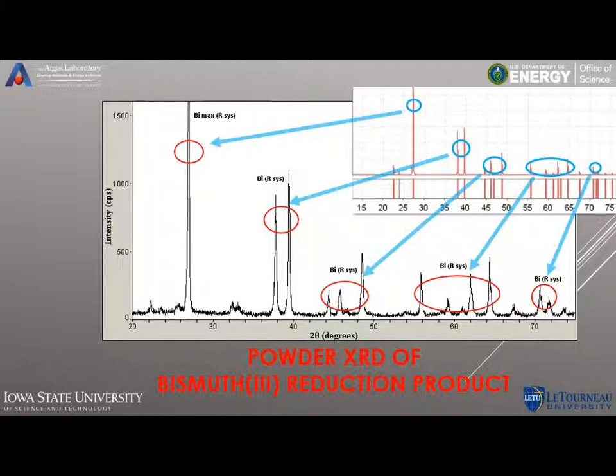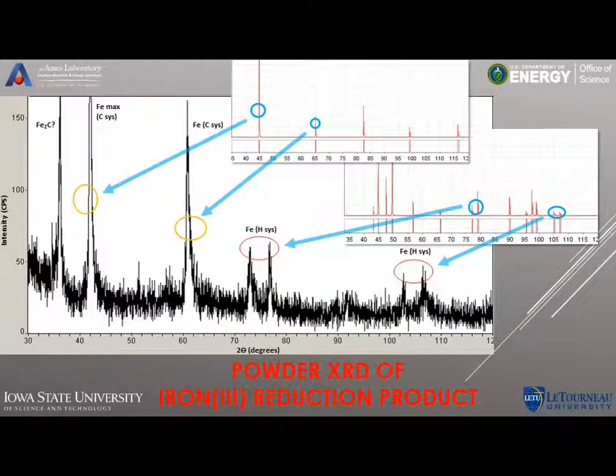Now this is an X-ray diffraction spectrum of the bismuth reduction, and you can see that I matched it to a reference spectrum in a database and found that I'm getting consistent peaks for the pure metal bismuth. The iron was a little bit more difficult just because sample preparation was more difficult. I had only small fragments of the metal, and iron is considerably harder than bismuth, as you may well know. So what I was doing to prepare the sample was to grind it with a file into small fine powder so that I could get a good reading.